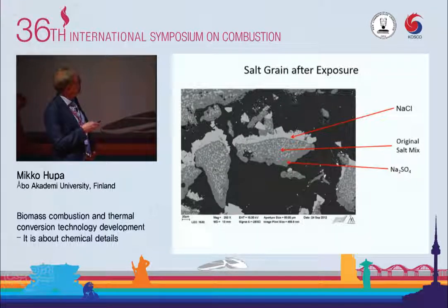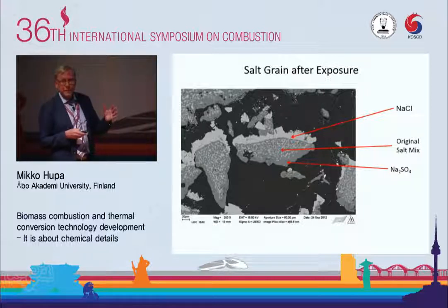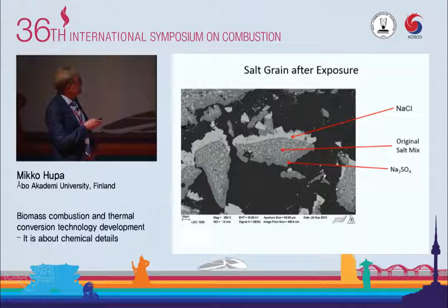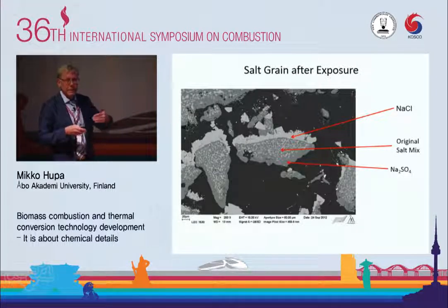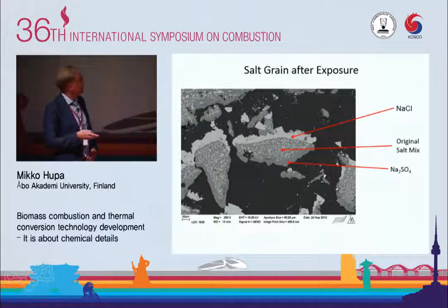So we have the sodium sulfate gray matrix and sodium chloride crystals in that matrix. They were prepared by melting and cooling, so that's how it looks. But with 24 hours in this temperature gradient, the sodium chloride started vaporizing and condensing to different particles, some kind of a vapor transport, which took place quite quickly.